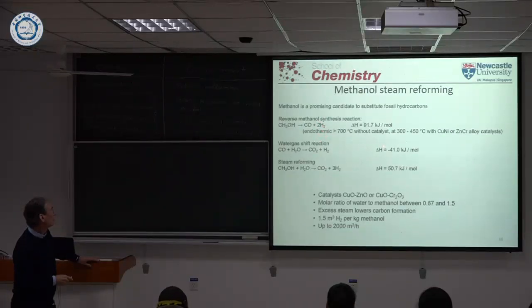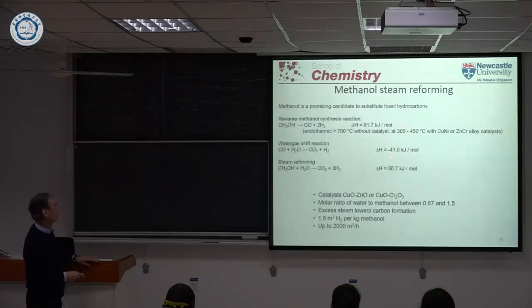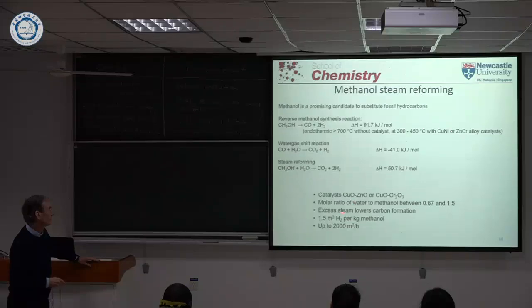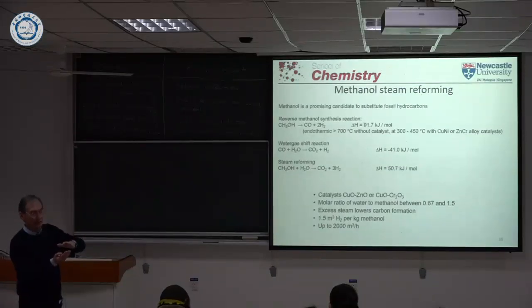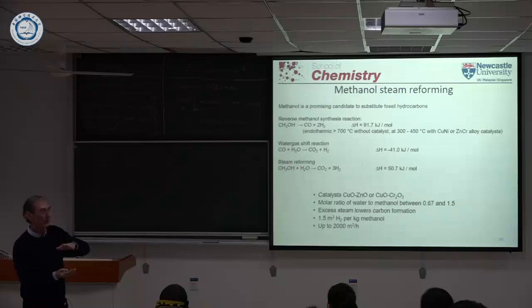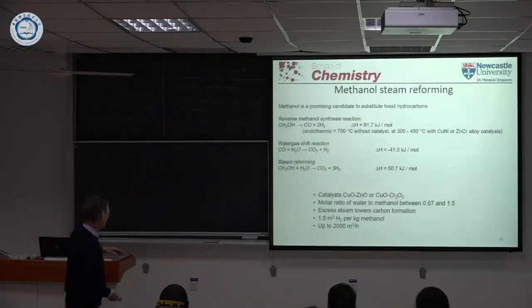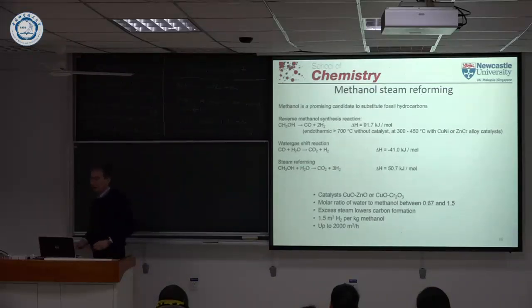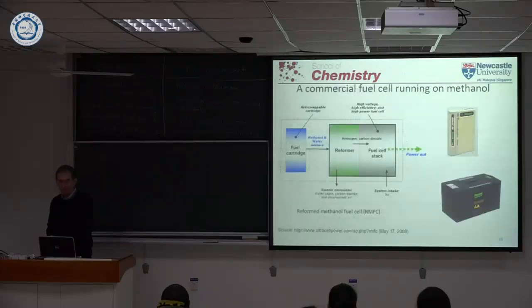because you can do the reforming at a temperature of about 300 degrees or even below that. So that's a big advantage. You still need the water-gas shift reaction, but you need only the lower temperature stage, because the operating temperature is much lower already. So in total, when you look at methanol steam reforming, these are the parameters for it. You can operate it at lower temperatures. You need only one shift reactor compared to methane, and that makes the process simpler, less expensive, but you have to know where your methanol comes from.